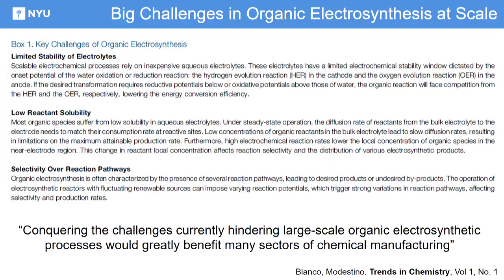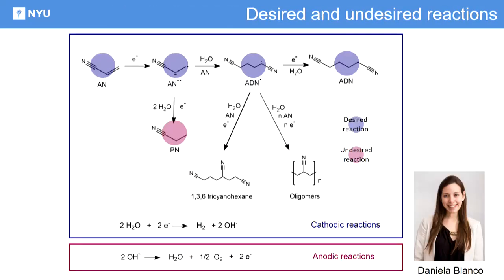Selectivity is a challenge because as soon as you inject an electron or subtract an electron from an organic molecule, then these things can actually do many things. And in the context of adiponitrile, this is what it actually looks like. So you can start with acrylonitrile and make a dimer, adiponitrile, but if you don't have enough of it around, you can actually get hydrogenated to propionitrile. If you have too much of it around, you can produce trimer or polymers of this molecule that you don't want. Then you have water, you can also evolve hydrogen in this reaction.